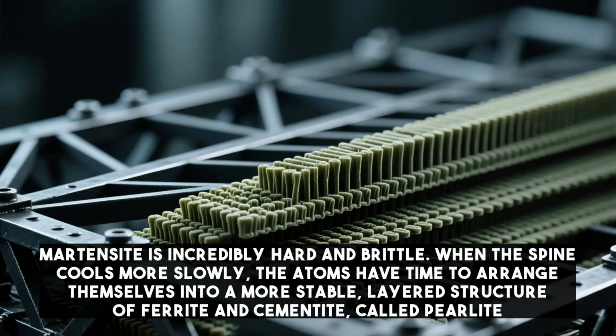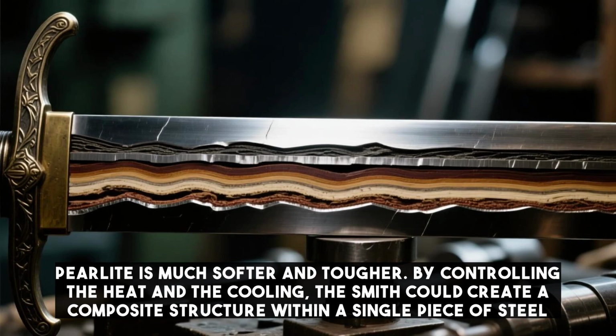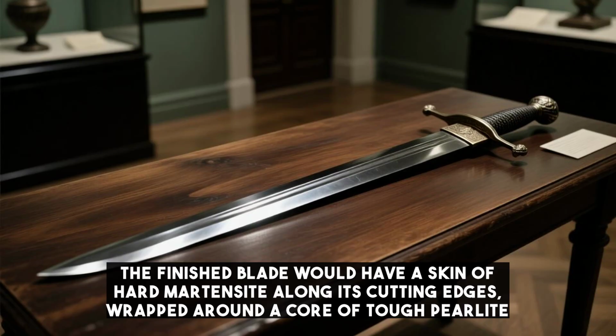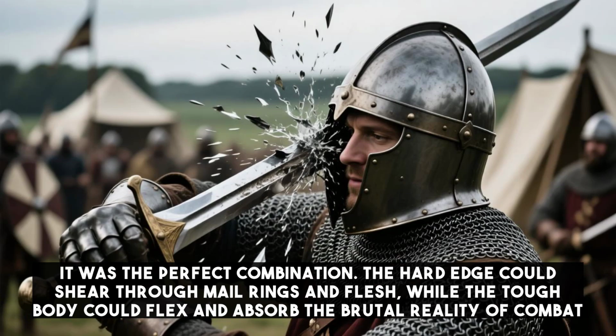When the spine cools more slowly, the atoms have time to arrange themselves into a more stable, layered structure of ferrite and cementite called pearlite. Pearlite is much softer and tougher. By controlling the heat and the cooling, the smith could create a composite structure within a single piece of steel. The finished blade would have a skin of hard martensite along its cutting edges, wrapped around a core of tough pearlite. It was the perfect combination.